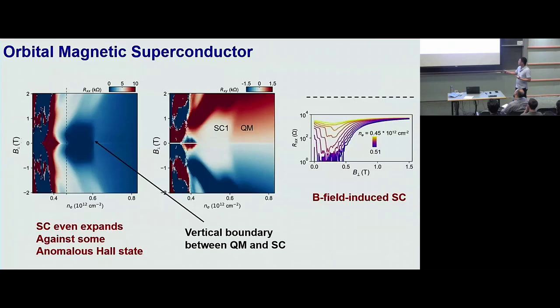However, what you actually found is that this right boundary here remains vertical when you apply magnetic field, outer plane. And the left boundary is even expanding a little bit, okay? That means the superconductor is even expanding to a region that was not superconducting at 0 magnetic field. So instead of magnetic field killing superconductor, for a little range of magnetic field, superconductor actually got stabilized.